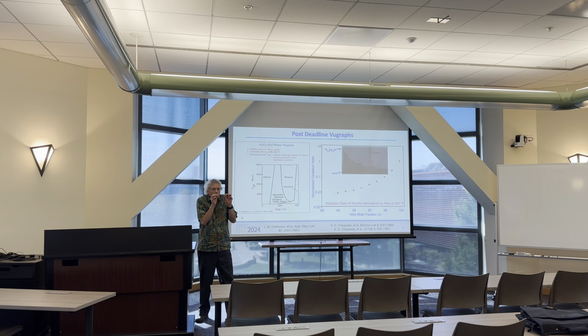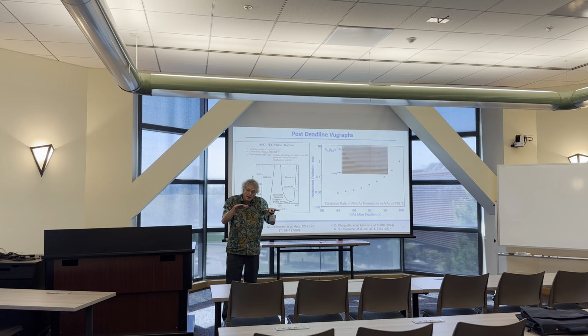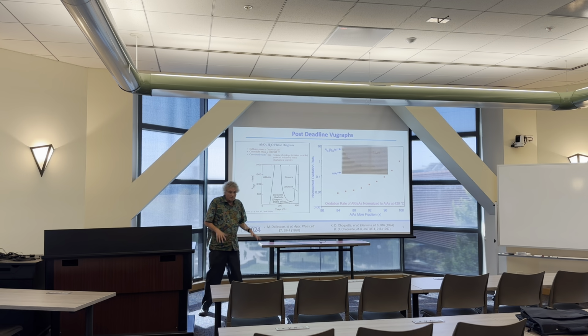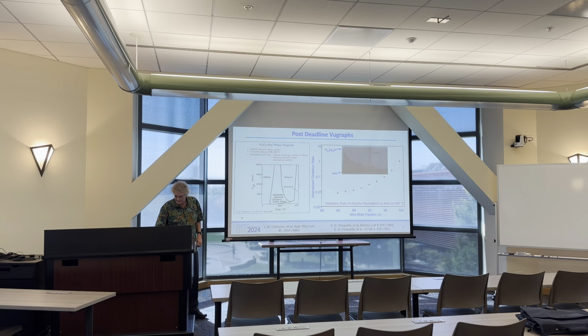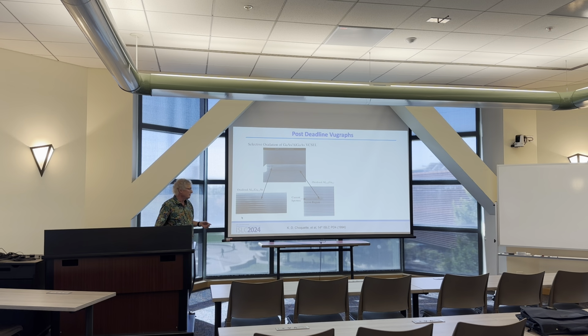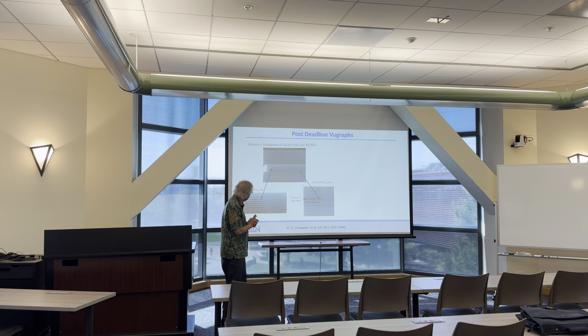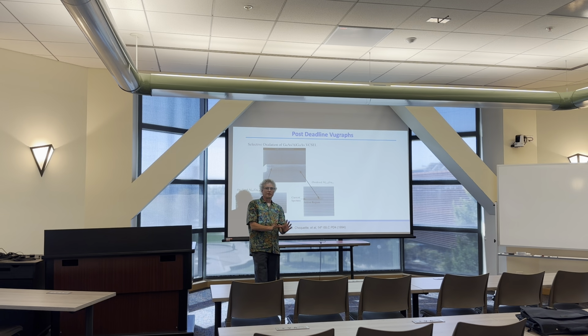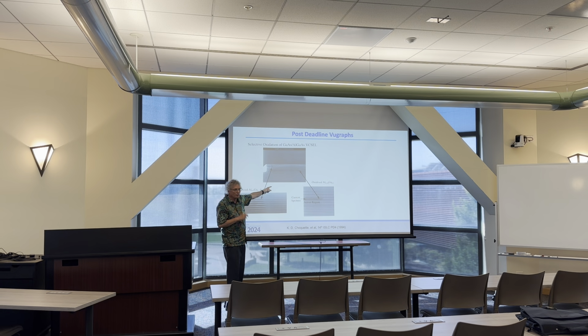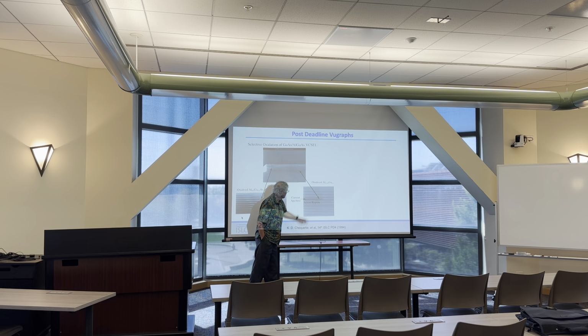And what this allows you to do is, through tiny changes of composition, you can very much control this oxidation extent. This was before we got the TEMs going. We had just got one of these cool thermal printers on the SEM, so I could do some work at night, which you can no longer do at Sandia in the clean room. I could look at the cross sections and print out these little printouts, and so we could see these oxidized layers in the stack, and then we made this our oxide.